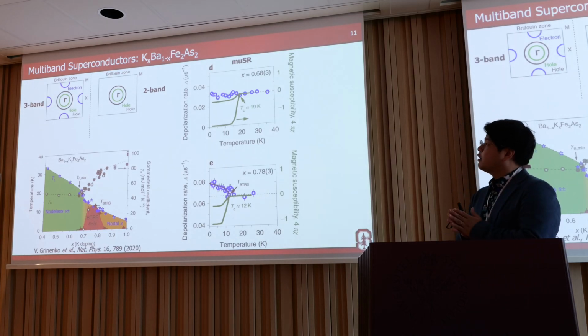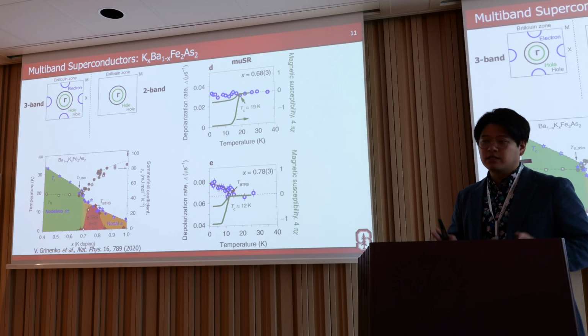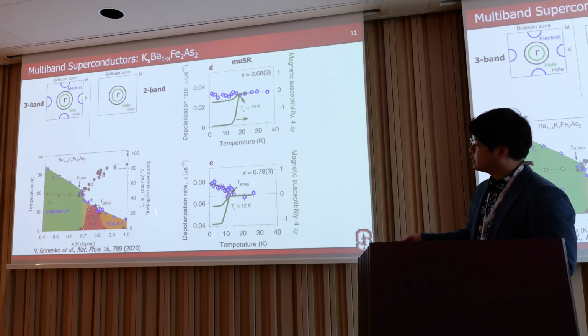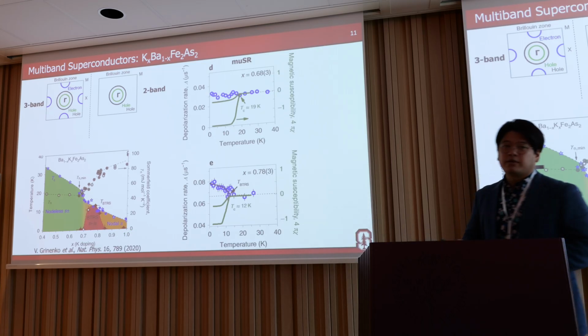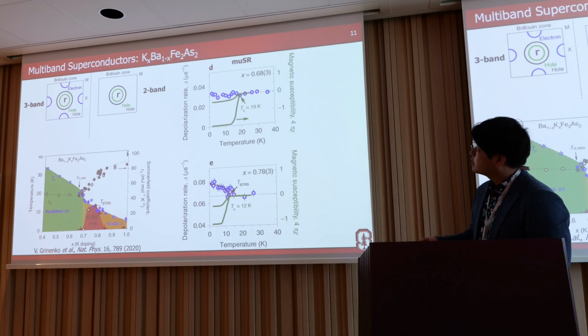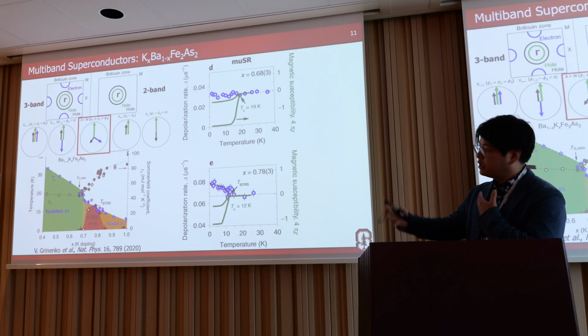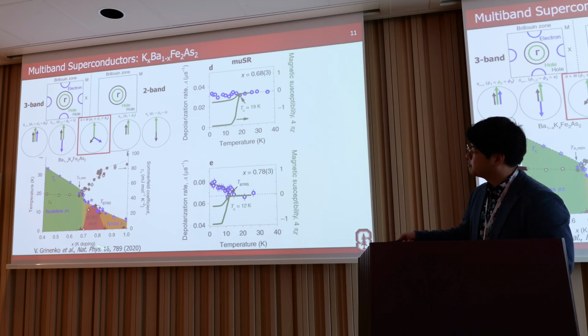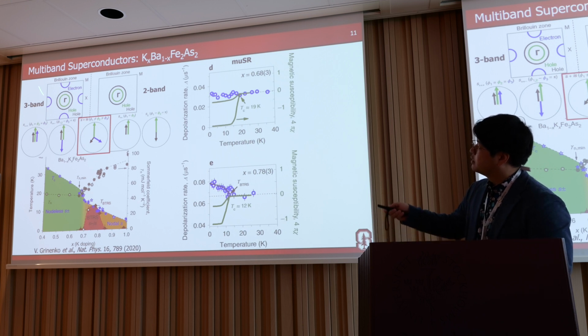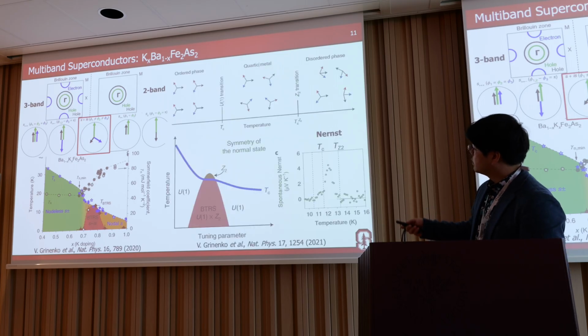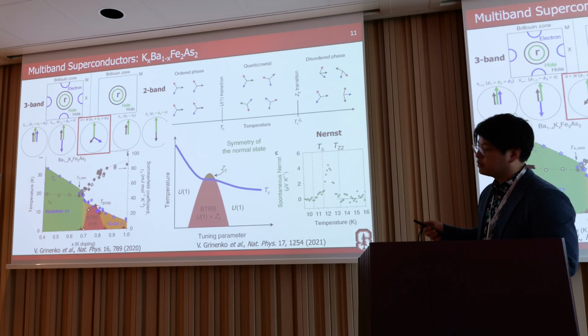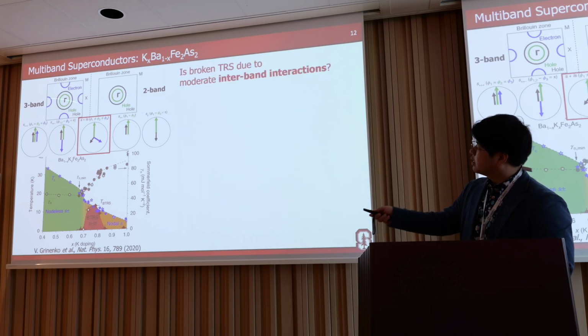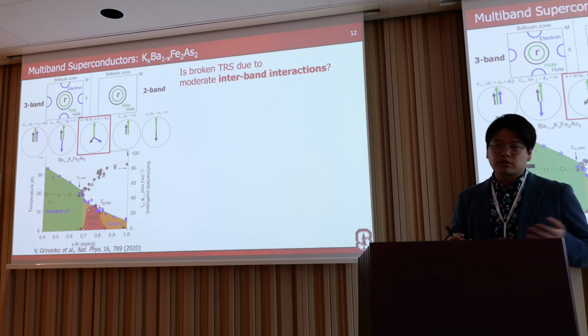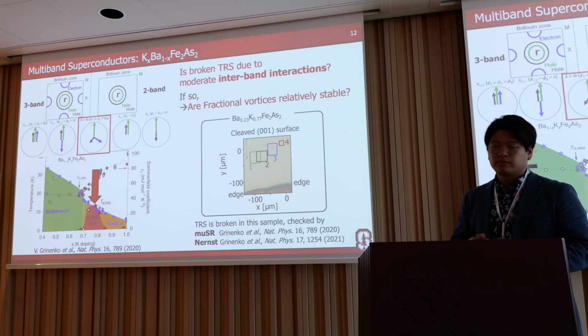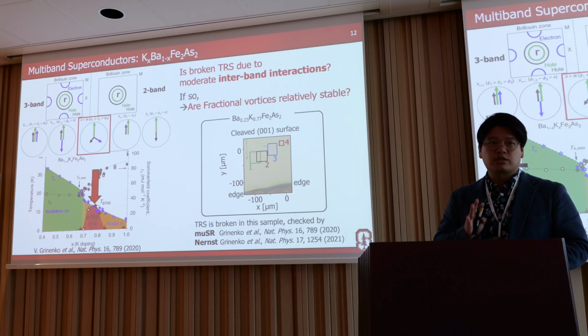Okay. Our group has measured many kinds of multiband superconductors, but we've never seen a fractional vortex. Here we focus on this material because time-reversal symmetry breaking measured by muon spin relaxation suggests the s+is state is stable, because the flux ratio is maximum around this region, because of the lifted transition from three bands to two bands. They also measured fluctuations in a nearby measurement and suggest a quartic metal. If it's true that it originates from very moderate interband interaction, then maybe fractional vortices are also stable. That's our basic motivation to measure this one.